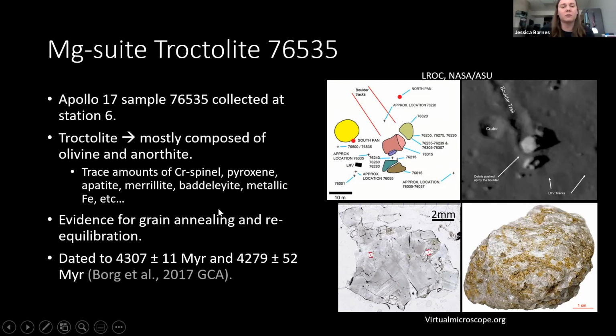So this particular troctolite is mostly composed of olivine and anorthite, as I mentioned, but it also contains trace phases like apatite, merrillite, and there's some baddeleyite in there as well. This sample, you can't really see it in the transmitted optical light micrograph, but what we see in this sample is a lot of grain annealing and some re-equilibration. And this sample's old. It's been dated to about 4.3 billion years old.